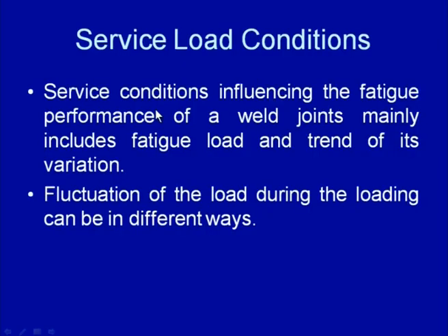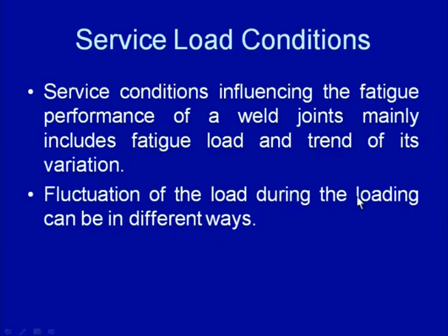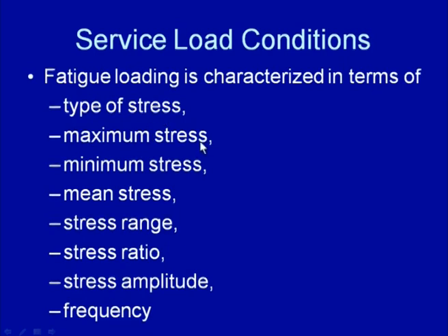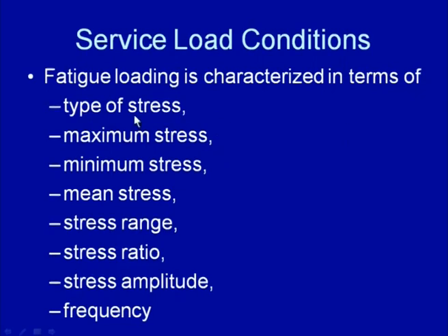So, as far as service related factors are concerned, service conditions influence the fatigue performance of the weld joint, mainly including load and the trend of its variation. The fluctuation in load during loading can be in different ways, and this fluctuation is observed in respect of the type of stresses, maximum stresses, minimum stresses, mean stresses, stress range, stress ratio, stress amplitude, and the frequency. The tensile stresses adversely affect the fatigue performance as compared to the compressive. The compressive stresses sometimes even decrease the fatigue fracture tendency and improve the fatigue life.